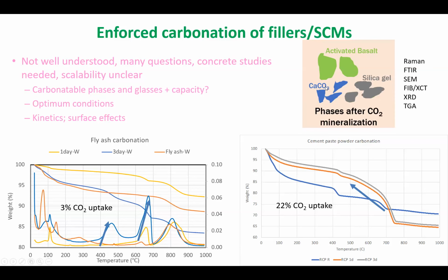And then at 3 days, the peak increases significantly. But also, this is a little interesting because you almost see 2 different peaks here. So presumably, we formed 2 different kinds of carbonate.